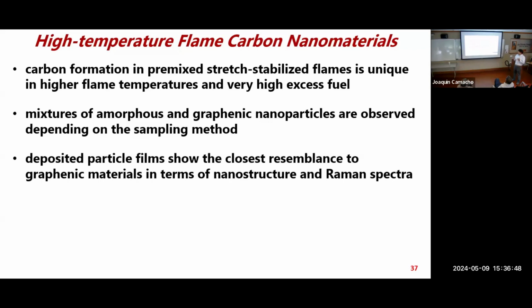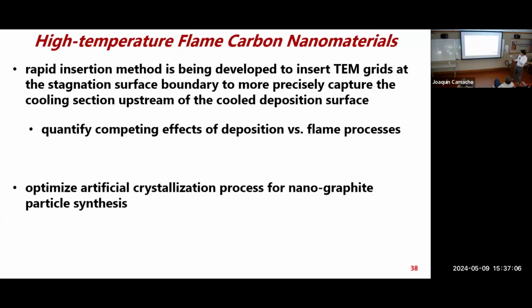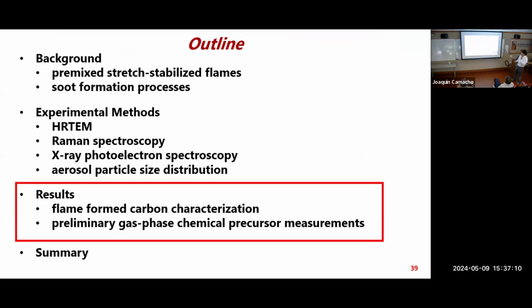And there's a lot of work to do to separate all these competing processes. And there's a mixture of graphenic, amorphous, and typical soot. But definitely this is evidence that these high temperature flames give you a different regime than typical soot formation. So I was doing work to quantify all of these competing effects.